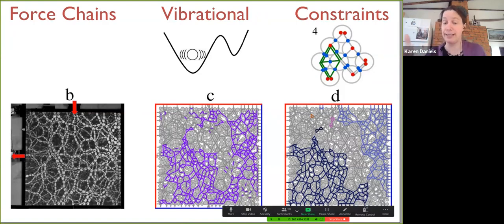This experiment was done with static steps, okay? But if we take it further, we can see that there's a chain of energy minima that a particle might transition between, okay? That's a different way of thinking about failure than thinking about Coulomb failure, right? Coulomb failure is if you have ceased to satisfy your friction threshold, you've exceeded it, then you'll have slip at that point, right? And you will have exceeded the threshold force as opposed to exceeded a threshold energy. Okay, so these are two different ways to think about the problem.